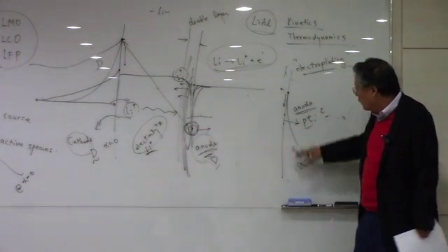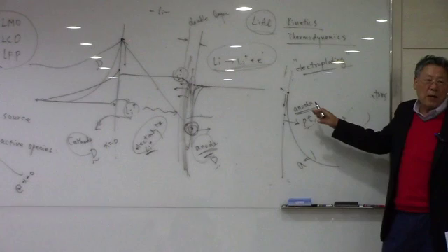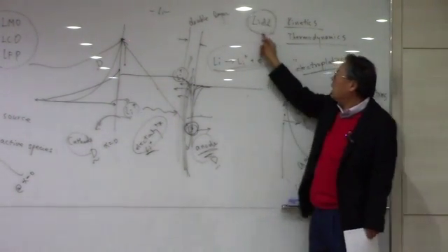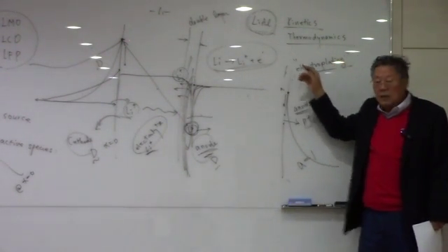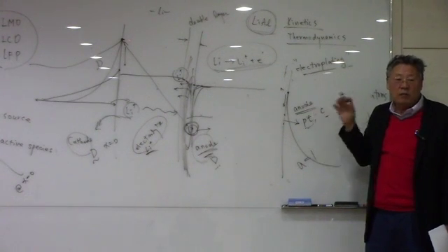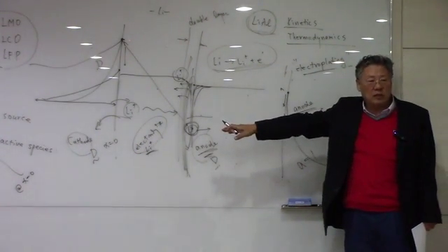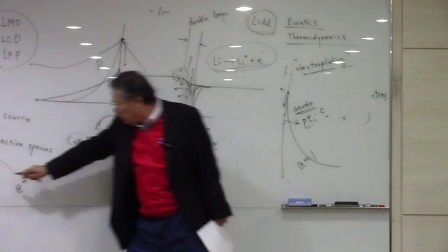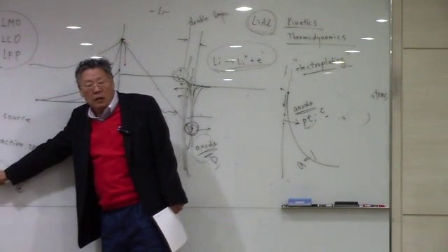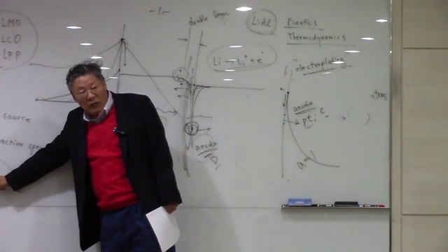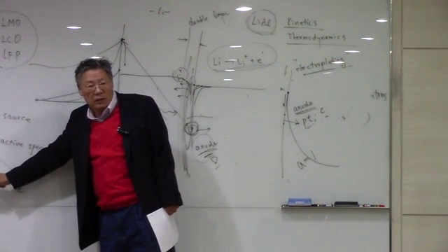Actually, if you use compounds of lithium alloys like this, instead of a lithium metal, then you have to sacrifice some of the voltages, because this activity here in the numerator is not 1.